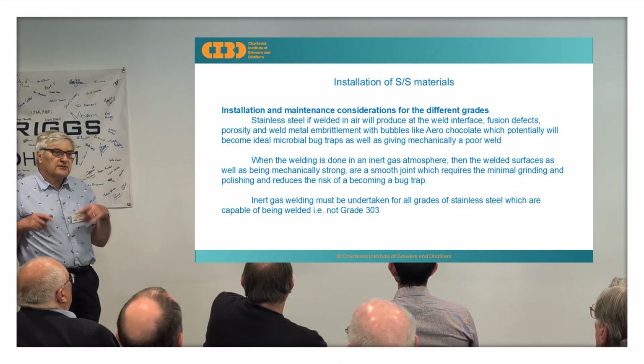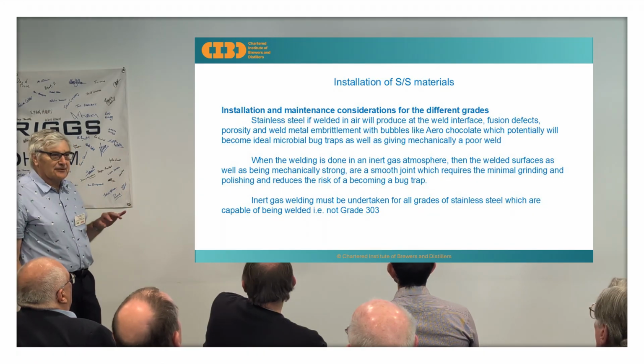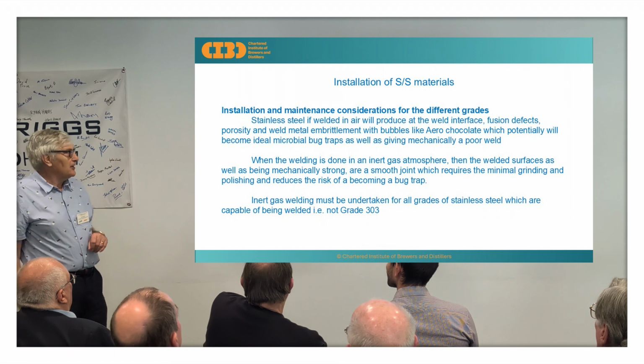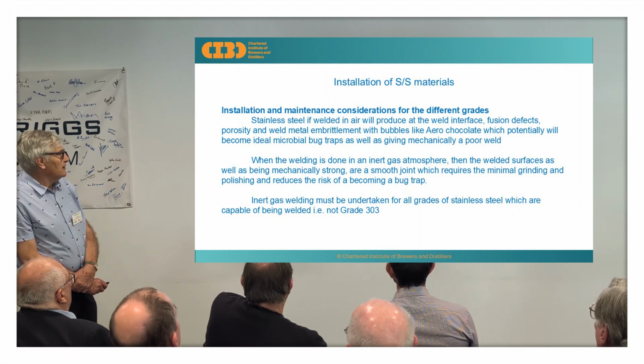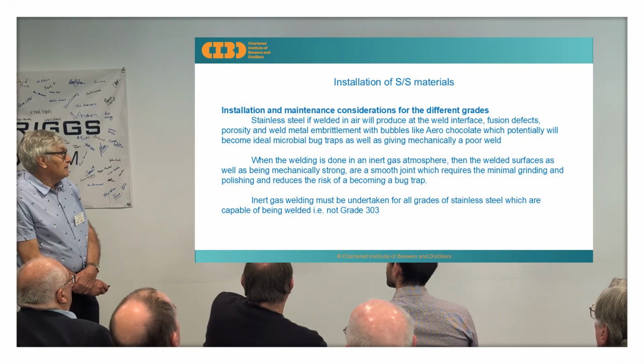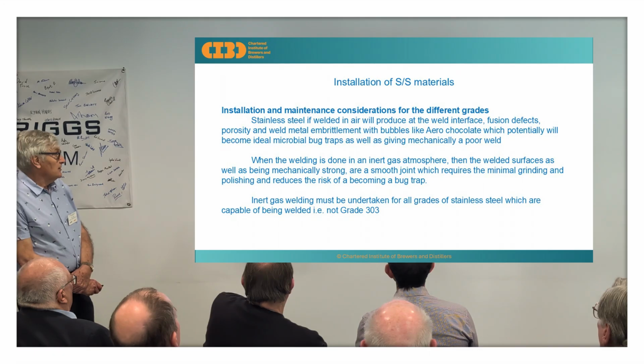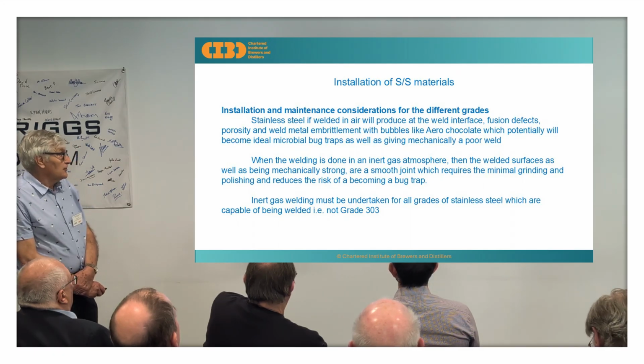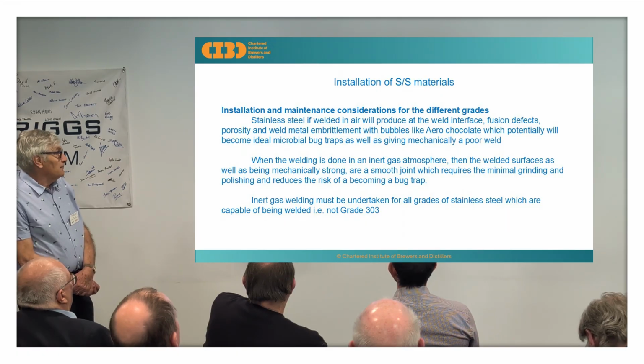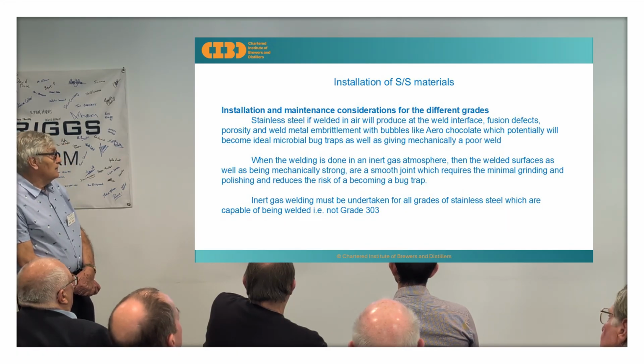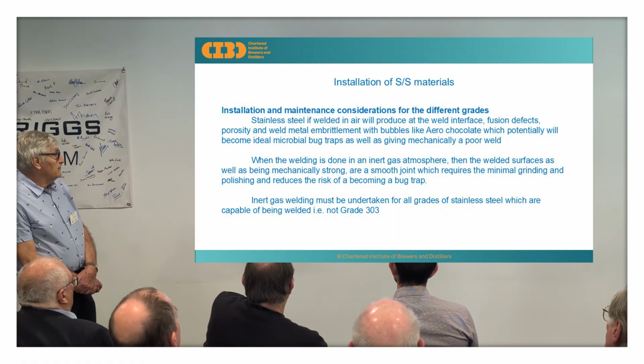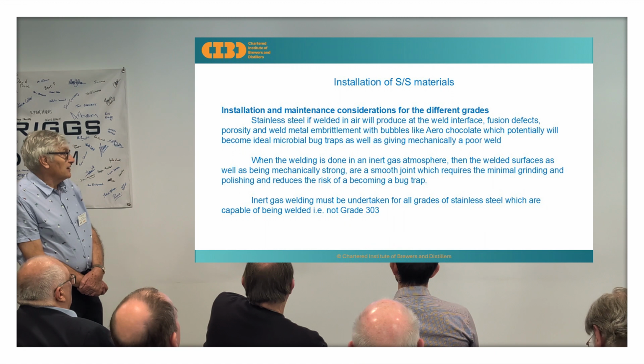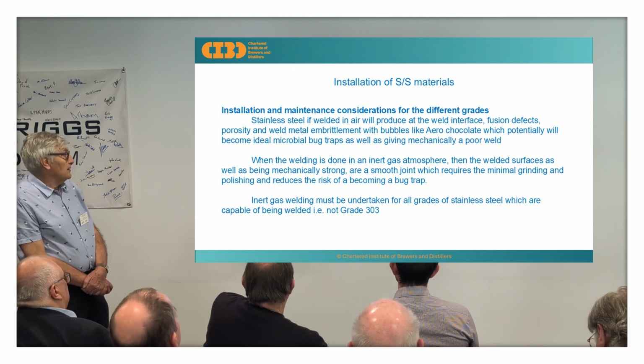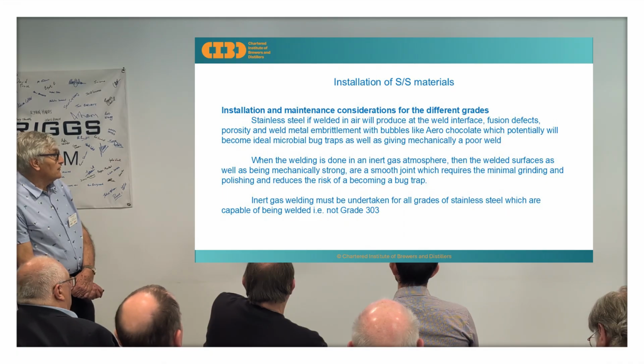Bear in mind this is aimed at students doing exams, so probably you already know about this, but this was to point out that welding of stainless steel is really only able to be done sensibly and professionally in an inert gas, where the welding surfaces will be mechanically strong, you get a smooth joint, and it requires minimal grinding and polishing and reduces the risk of any crud traps. Gas welding must be undertaken for all grades of stainless steel which are capable of welding, but not grade 303, as we said before.